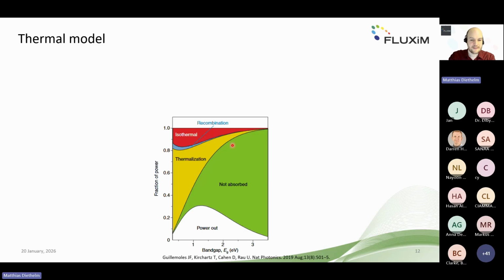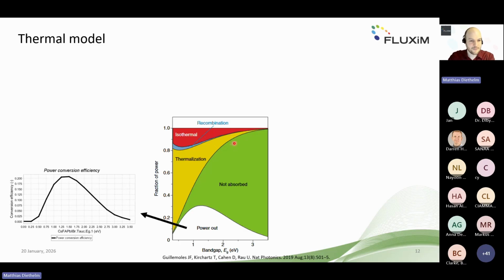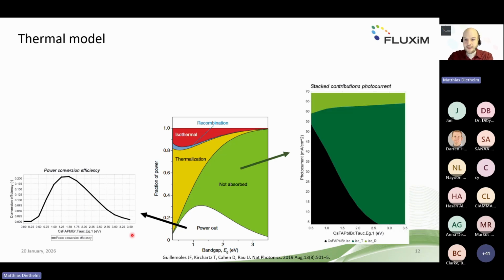So to look into this, I set up a quick model. It's not the full Shockley-Queisser model in Setfos here, because we still have optical losses, as I was modeling the optical part still with a realistic refractive index. But you get the same trend here with the model when shifting the band gap of the perovskite, as you can see, for the power conversion efficiency. You can look at the photons which are not absorbed. So the dark green here is transmitted photons through the device which are not absorbed. So you see here there's still some reflection. That's not part of the Shockley-Queisser model, for example.